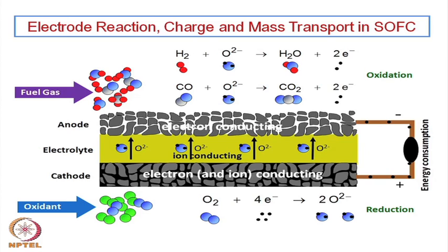One has to choose a very stable oxide, which is stable not only at a highly oxidizing condition like pure oxygen, but also a highly reducing condition like pure hydrogen. So, this is once again a challenge, but fortunately we have that kind of material in the form of stabilized zirconia. Zirconia is a highly stable oxide, its melting point is very high, and at the same time its non-stoichiometry is extremely low. That means it does not get oxidized or reduced either in the presence of hydrogen or in the presence of oxygen.